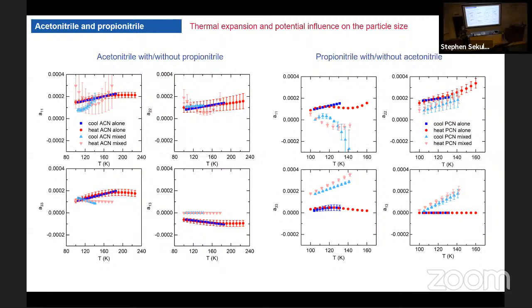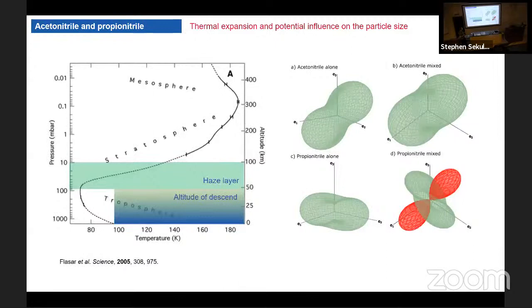Normally, when you heat something, because of vibrations, things are expanding. Hence thermal expansion. But if we take a look, we have quite interesting behavior of acetonitrile and propionitrile, and this might be a little bit of a better representation of the thermal expansion. So the first thing that you can notice is a very pronounced anisotropy of thermal expansion, which is not very common. Commonly, solids would expand in every direction pretty isotropically. But in this case, because of how the crystal structure looks, they expand completely anisotropically. Moreover, propionitrile, the metastable high temperature monoclinic form, is also featuring negative thermal expansion. It's uniaxial. Uniaxial negative thermal expansion is unusual, yet it's understandable from a structural point of view.